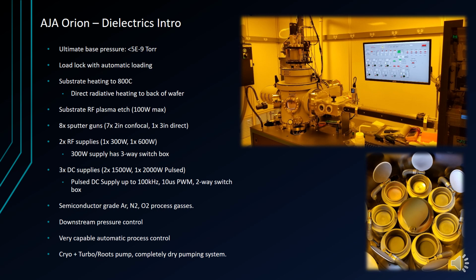This sputtering system is UHV, with an ultimate base pressure less than 5e to the -9 torr. The wafer loading is fully automatic. Substrate heating is achieved by direct radiation to the back of the wafer and can sustain temperatures up to 800 C uniformly across a 6-inch wafer. RF bias up to 100 watts can be applied to the substrate for in situ cleaning, oxide removal, and etching. This may be performed with any of the available process gases.